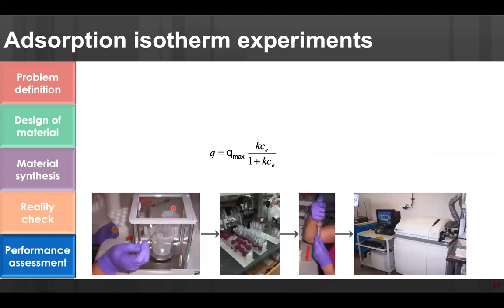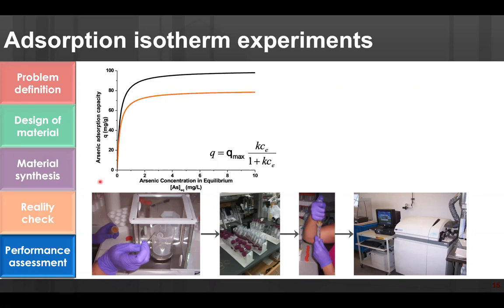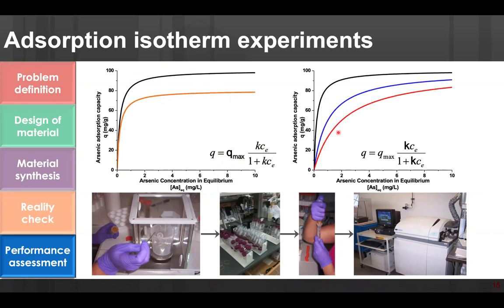And the way that I do the absorption isotherms is you weigh the absorbent, you expose it to a solution that has arsenic, you remove the solid, and then you measure the amount of arsenic that you have. Based on that experimental data, you try to fit it to a Langmuir isotherm, where two parameters are important: the maximum capacity that the material can absorb. In this case, for example, a bigger capacity gives me this black line instead of the orange, and a larger Langmuir constant, that is basically how fast I can saturate the material at lower concentrations.